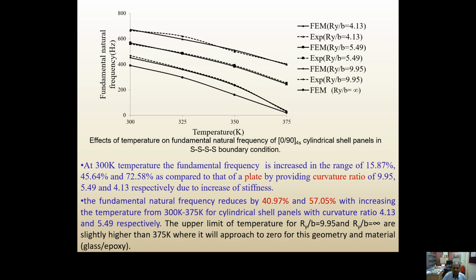So at 300 Kelvin, the fundamental frequency is increased in the range of 15.87%, 45.64%, and 72.58% as compared to that of a plate by providing curvature ratios of 9.95, 5.49, and 4.13 respectively, due to increase of stiffness. The fundamental natural frequency reduces by 40.97% and 57.05% with the increase of temperature.